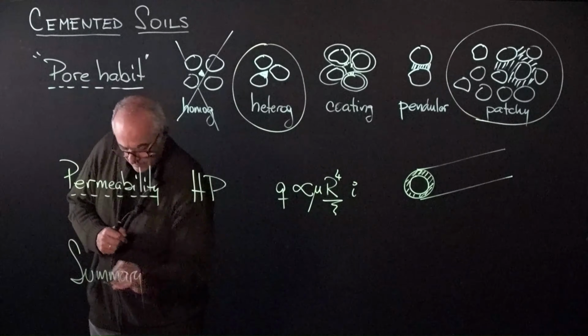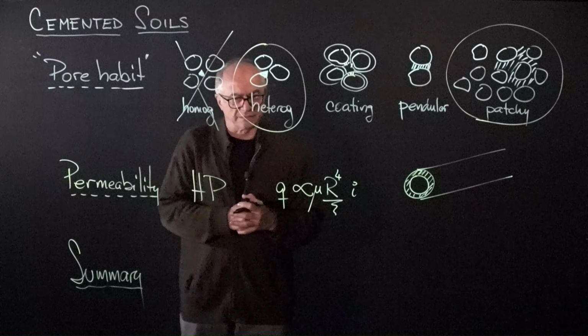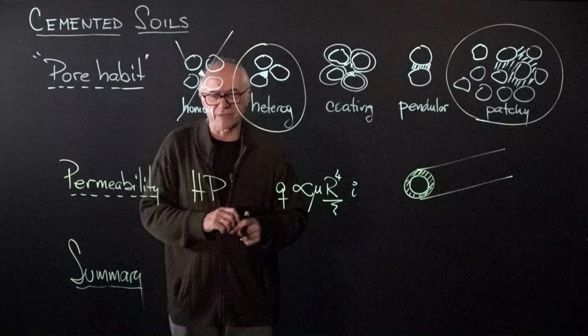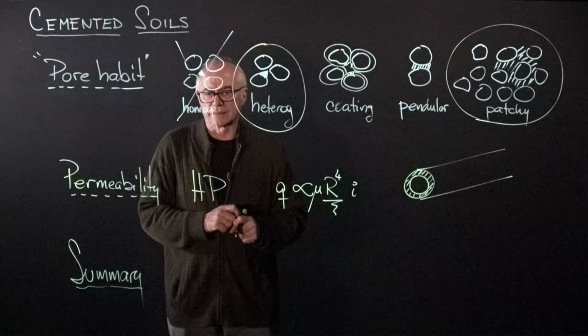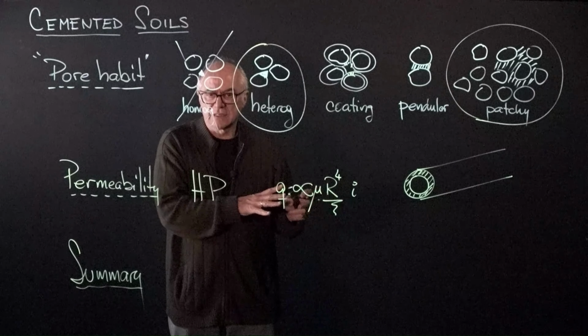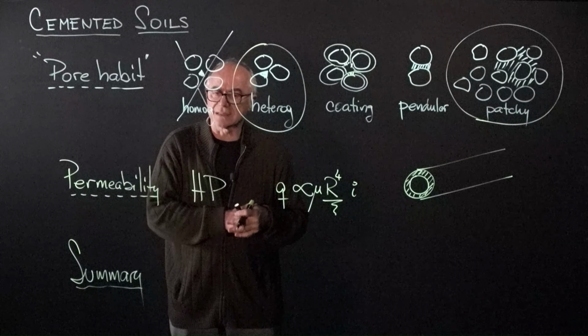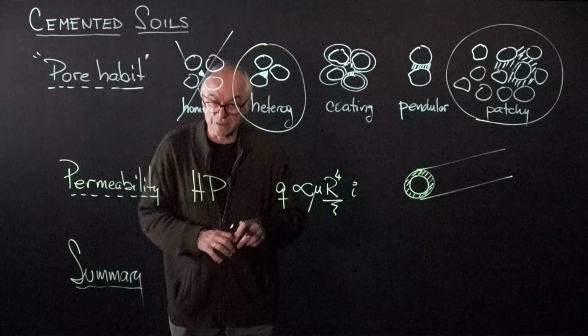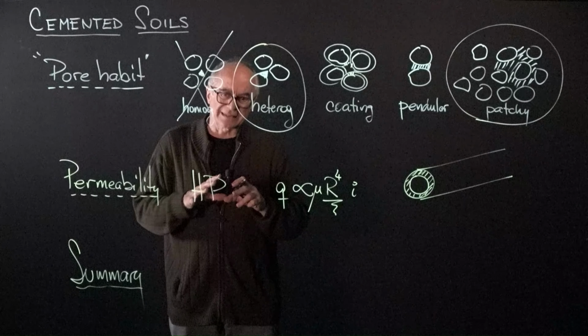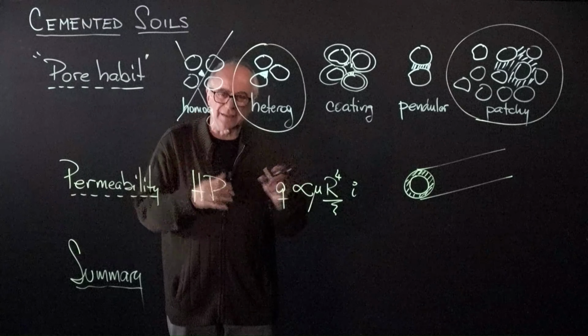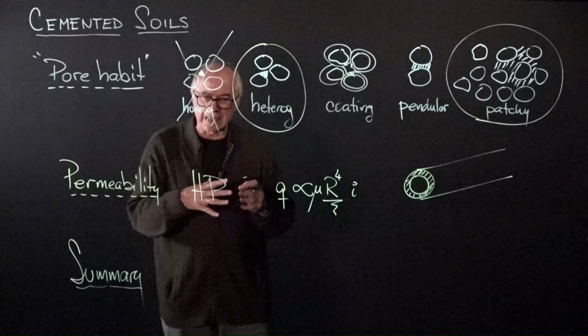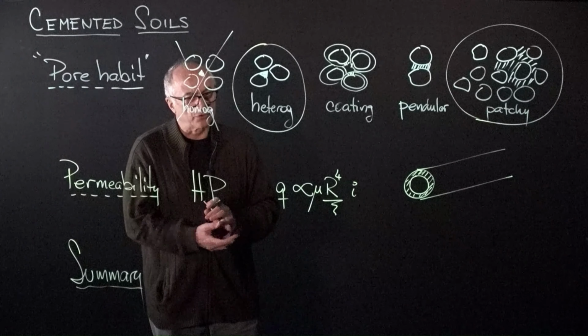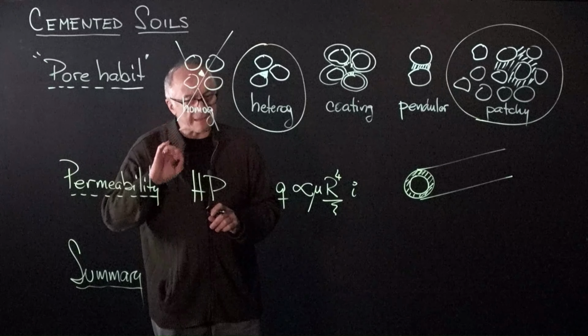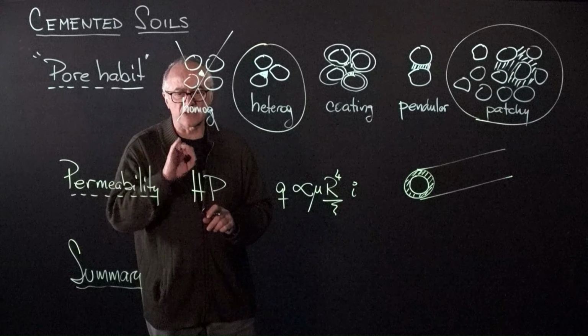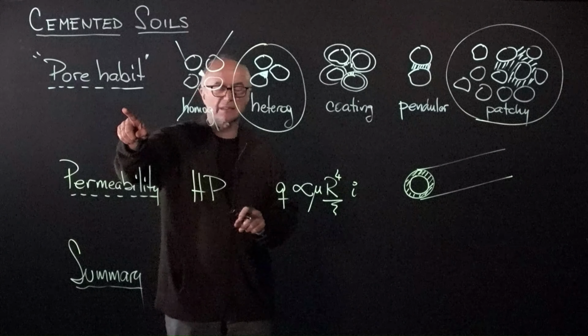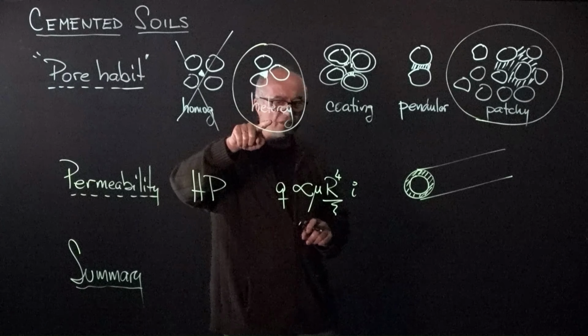To summarize, cementation affects all our properties. It has primarily a very strong effect on small strain stiffness. Gradually, cementation will begin breaking down, but still has a very important effect on the large strain properties. In particular, dilation, as the system is beginning to break down because of the blockiness of the cemented structure as it evolves towards failure conditions. Two important parameters are not only the amount of cementation, but how did the cementation form within the pores, the pore habit. Most likely, it started as heterogeneous nucleation.